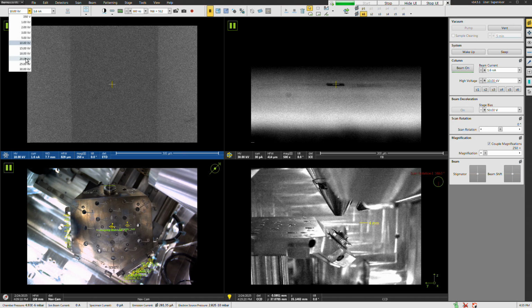Okay. But anyways, not much gained, I believe, by going higher than 20, but you can gain spatial resolution by going below 20 down to 10. Okay, I know for this sample, this is an Inconel 600 that actually has a cored microstructure, so the middle of the puck here actually has a fairly fine microstructure, so I'm actually going to use 10